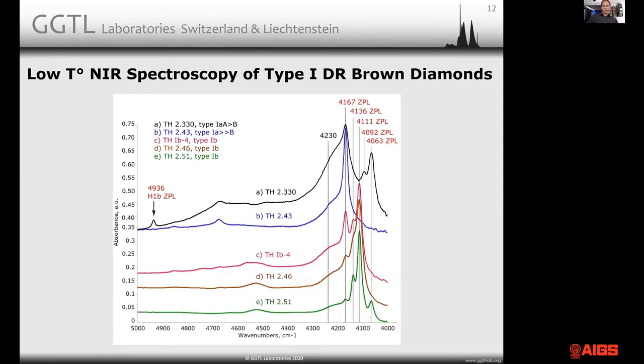Here a close-up. So this is the samples, just the zero phonon lines themselves, and you can see how they look like. So there is one that's absolutely characteristic for type 1B diamonds. That's the one at 4,111 wave numbers. The other ones can be present in type 1As or in type 1Bs. The 4111 zero phonon line I have not yet seen in a type 1A diamond. It always seems to need single hydrogen in order to produce this one. The other ones can be found in any type of diamond. 4136 I'm not quite sure about.